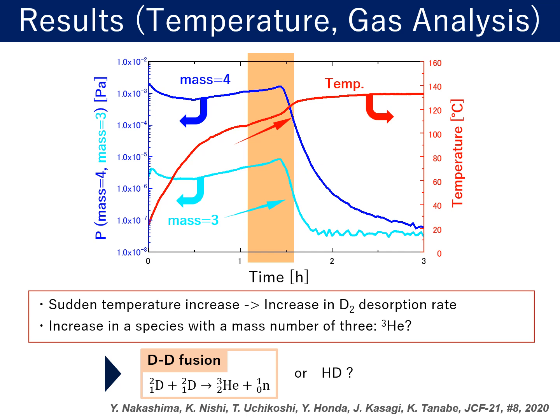As the experimental result, we observed a sudden increase of the temperature of the palladium sample and also an emission of gas species of mass numbers of 3 and 4. The species of a mass number of 4 was identified as helium-4 as a shoulder peak on the deuterium peak. The species of a mass number of 3 could be helium-3 or HD.